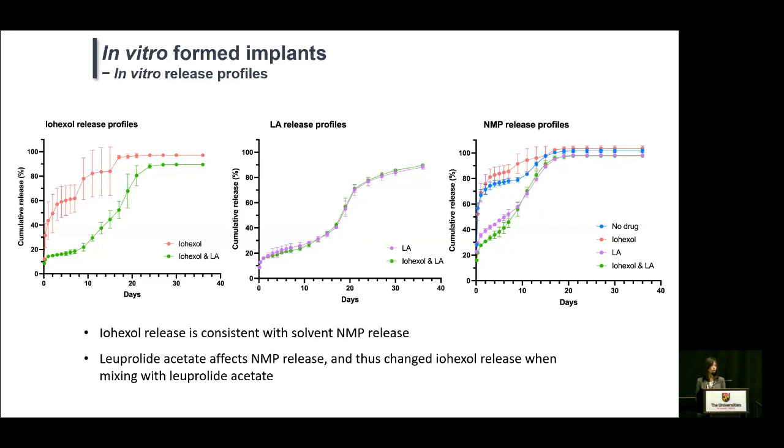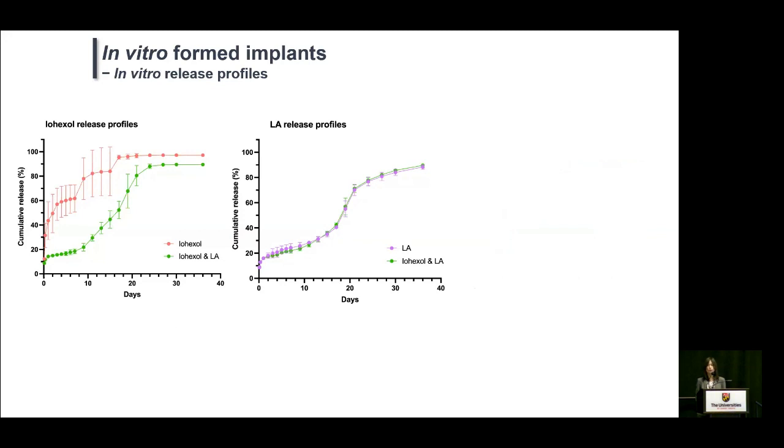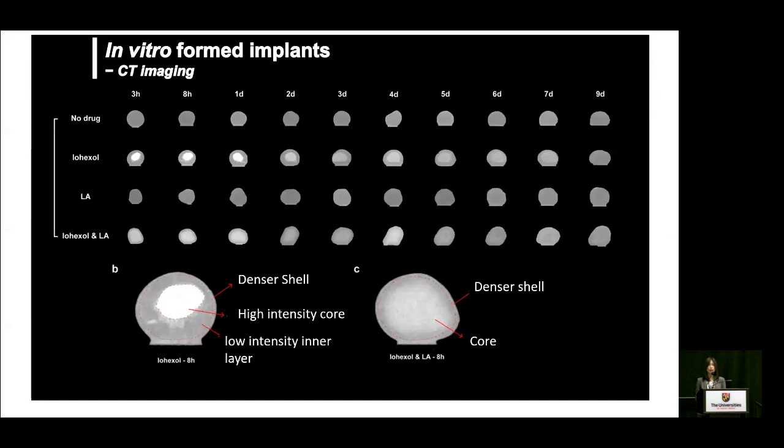I want to go back to this. The image shows you this is a fast phase inversion process. I appreciate Dr. William Smith's talk about the phase diagram and the phase inversion process, which applies here. You get very fast phase inversion, and then the rapid drug release together with the NMP release gives you this layer.